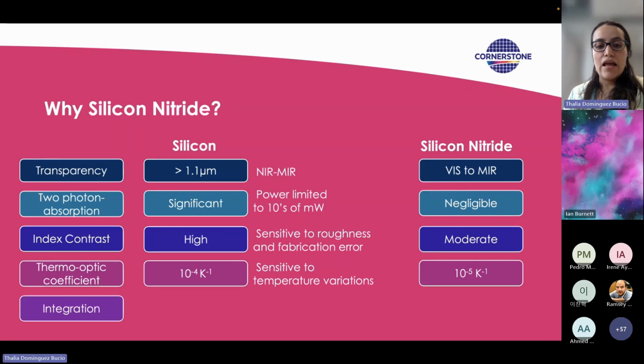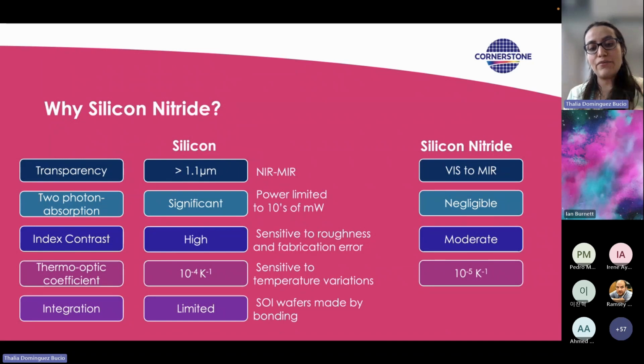And finally, one of the most important properties limiting silicon itself is that silicon, as we typically use it in the crystalline form, is fabricated in SOI wafers that are bonded. So it's very difficult to integrate this material with other materials, unless you start doing other kinds of deposition of silicon to get amorphous silicon or polycrystalline silicon, which will inherently increase the losses of your devices, unless you do very complex processing techniques to try to reduce the losses. Silicon nitride, on the contrary, is very flexible. It has the potential to be integrated in multi-layer schemes.